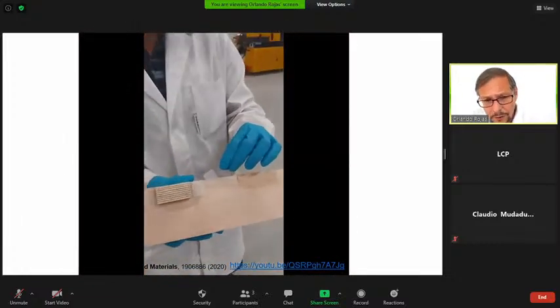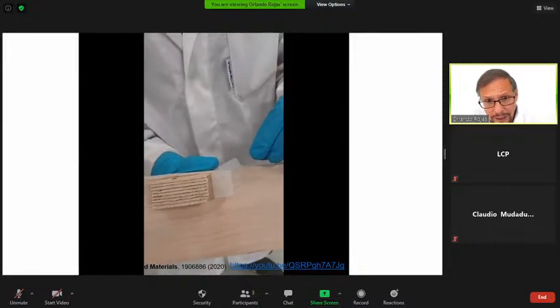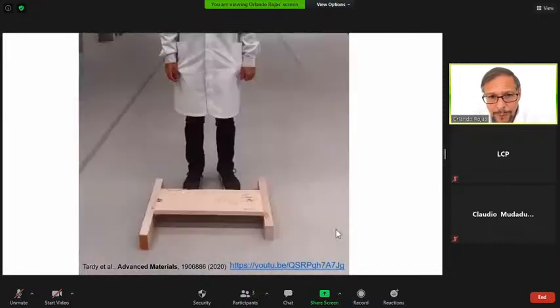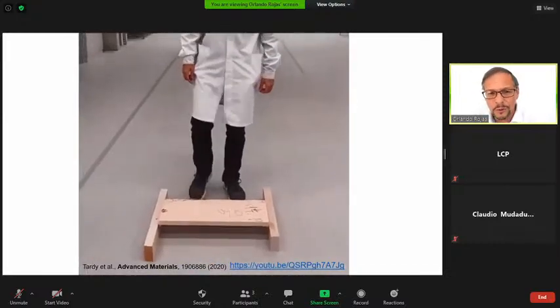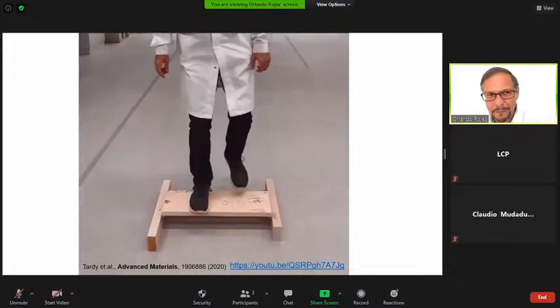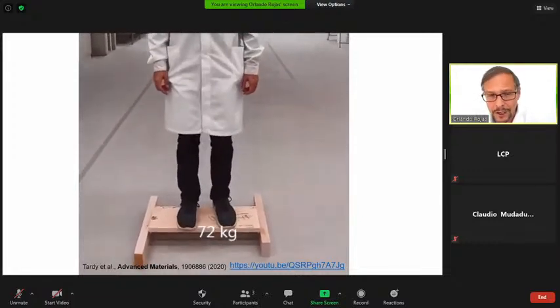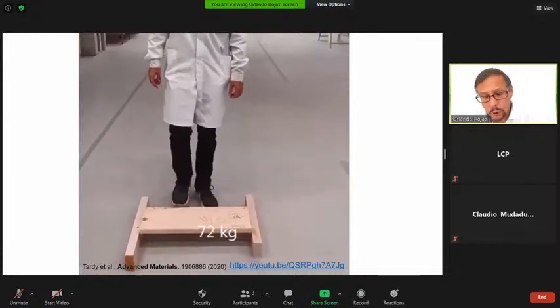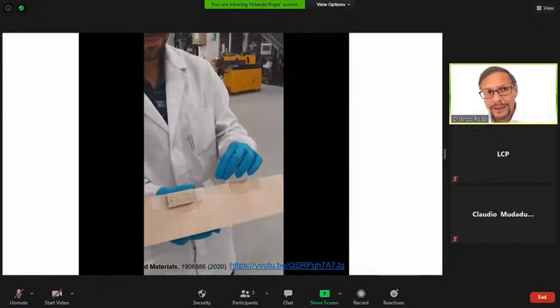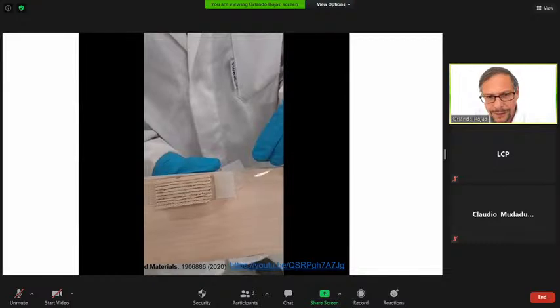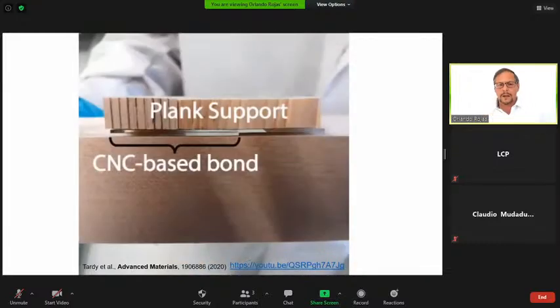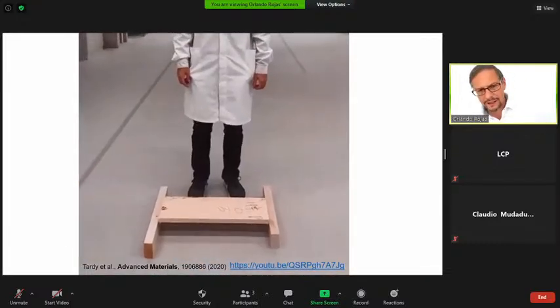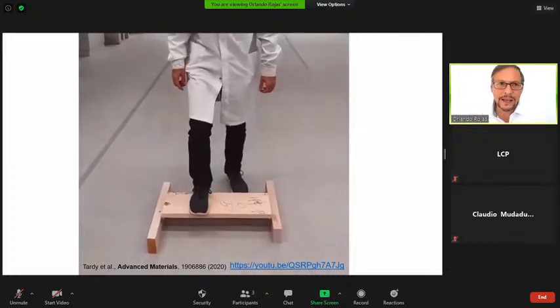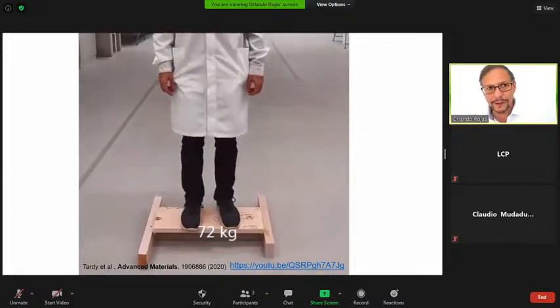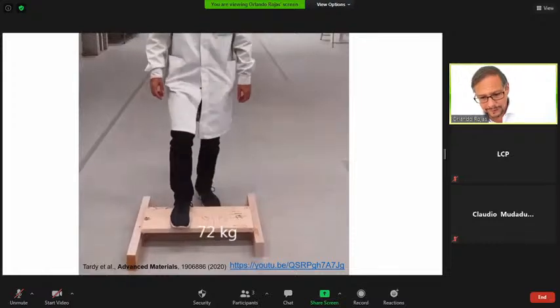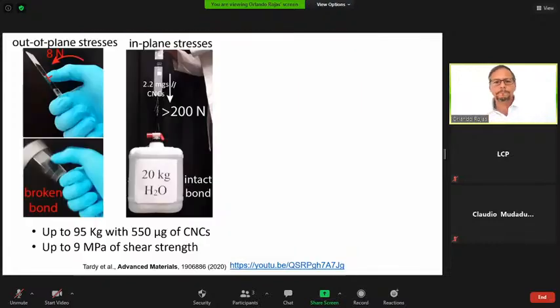So it's very nice because it's very strong. Yet, as you can see here, with a normal force, it's very easy to remove the material. And this is very important in many electronic applications, electronic components, where you want to have very strong glue in the shear direction, but not in the normal direction, as Luis showed here. So these are anisotropic glues, and they are shown to be of the same quality or better than commercial glues that are very toxic.